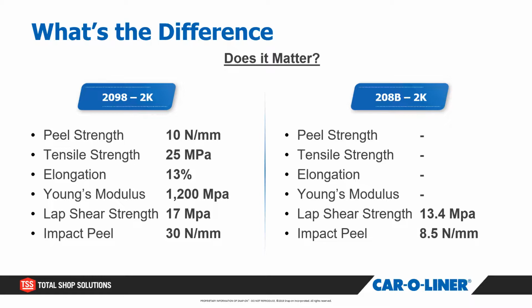And when you start looking at the compounding issue, say the technician didn't use the right rivets. They used the wrong structural blind rivets with the wrong grip range. And then they think, it doesn't matter what adhesive I use, I'll just use the panel bond because that's what I have. I don't have any 2098 on hand, I'll just grab the 208B. This is where you can have a big recipe for disaster, when you use the incorrect rivets that are called out in the OEM repair procedure, and then you use the incorrect adhesives.